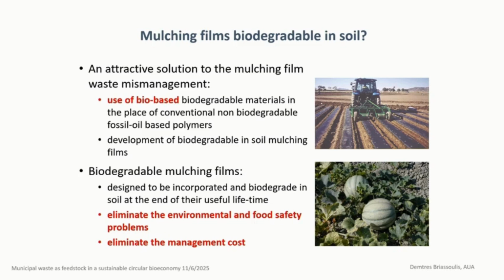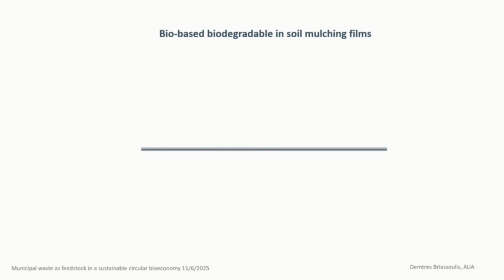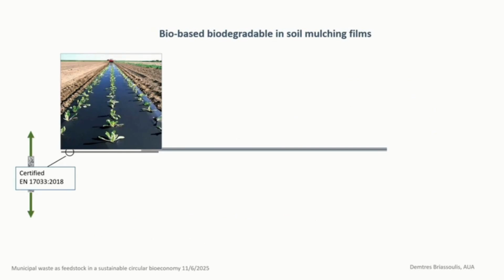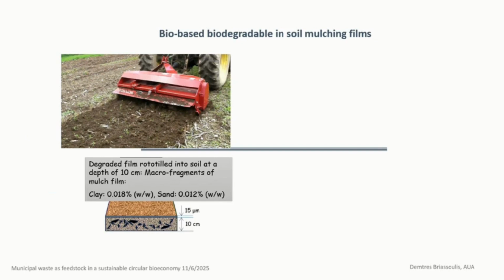But so far, the polluter pays principle is not applied to the farmers. So the farmers consider the conventional mulching films cheaper. This is a problem of the implementation of the legislation and the lack of infrastructure. Biodegradable in soil mulching films, certified according to European norm 17033, everything is fine during the useful lifetime, and at the end, they are rototilled, let's say in the topsoil, 10 centimeters thick, and we have a dispersion of the macro fragments of this degraded film into the soil at a low concentration, depending on the soil class, from 0.018 to 0.012% dry weight.